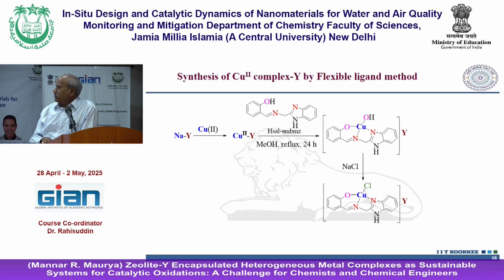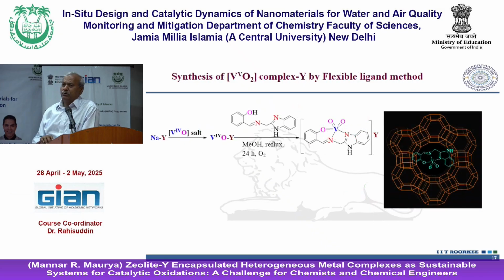Okay, and the same one, when you have a vanadium precursor, vanadium salt, treat it to get VO2+ exchanged zeolite, that is, vanadyl-exchanged zeolite, and then you add the ligand. In methanol, reflux it for say 24 hours in the presence of oxygen. You will ask the question, why is oxygen there? Now, sir, your question, vanadium 4 and vanadium 5.